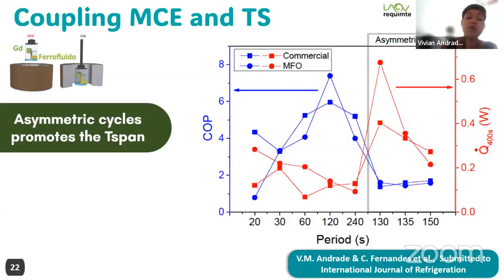And when we look at the coefficient of performance, for the symmetric cycles we achieved a COP value close to 8. And the simulations of the Kitanovski group reached 8.5. So even with a small device and using only one thermal switch, we could reach a COP value close to the theoretical one. So this is a good thing for our prototype.